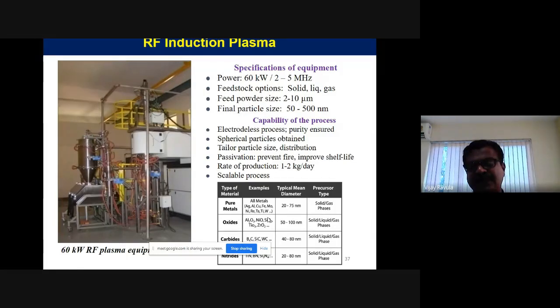So how do we achieve that? This is called radio frequency induction plasma. The top portion is where you feed the powder, or it can also be fed in the form of wire. And this is the plasma zone where you can get up to 5000 degrees centigrade. And when any material comes into that,